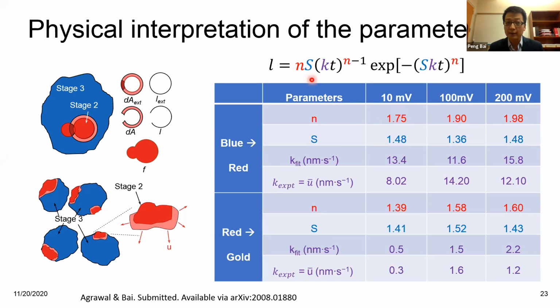But the S here, because we're analyzing the length of the interface, not the direct area, we have to adopt one shape factor. What I can tell you is that if S equals the square root of pi, that means you will have a perfectly radial, perfectly isotropic, or perfectly circular growth. And the square root of pi is 1.77. So you can see here, even though it's not 1.77, it's very close. And because we also see relatively isotropic, locally isotropic growth.